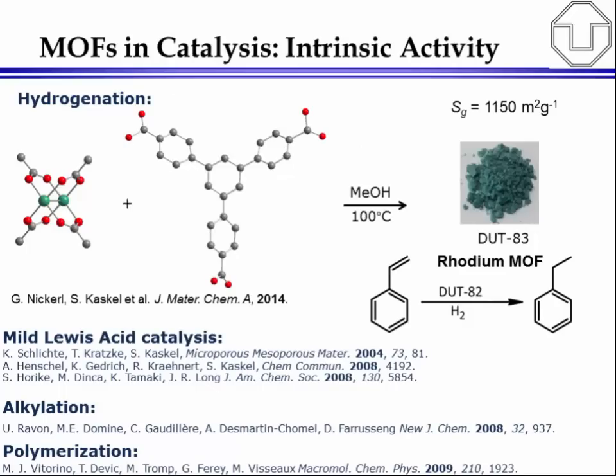it is not only possible to use the metal organic framework as a support for metal particles, but you can also, and this is I think the power of the MOF concept, you can also integrate active sites. For example, here we've integrated some rhodium type paddle wheels that show intrinsic hydrogenation activity, for example for hydrogenation of styrene, and this is of course one of the benefits that you can integrate also intrinsic active sites.